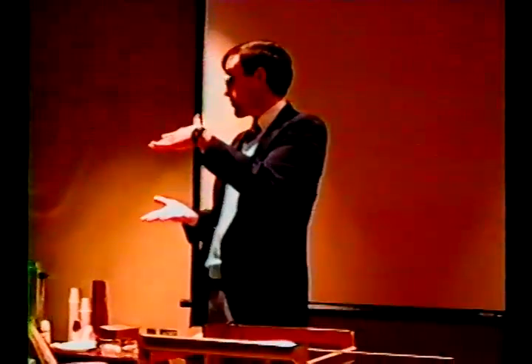Yeah, that's another key point. What's nice about the plasma is that blue glow. That blue glow can be traced to carbon monoxide. It fluoresces at a specific wavelength, and the blue is due to carbon monoxide. When all the carbon monoxide comes off, it's pumped out through the vacuum, it goes back to pink, which is due to argon. So all we really do is try to keep that plasma going long enough to break down all the carbon monoxide. We haven't done any prolonged irradiation in there.